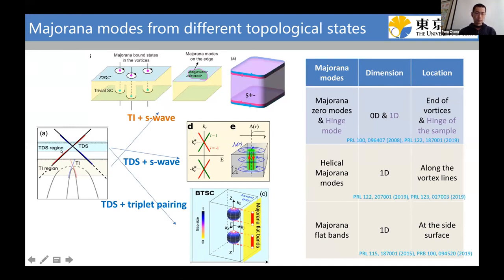If the Fermi level is located near the bulk Dirac band, in the case of S-wave superconductivity, we will have helical Majorana modes along the vortex line. In the case of triplet pairing, we will have Majorana flat bands at the side surface.